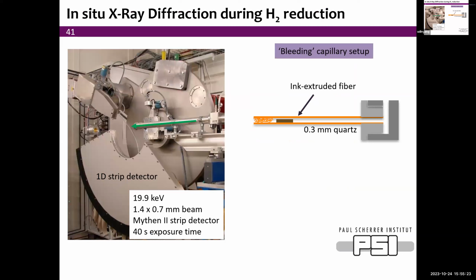So we wanted now to do some in situ X-ray diffraction during the hydrogen reduction. Why? Because we don't want to just look at before and after. We like to see what happens during the reduction itself. And X-rays will allow us to identify which phases are present. This was done at PSI in Switzerland, but we also did work at Argonne, of course, next door for us.